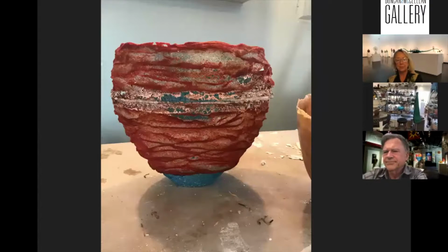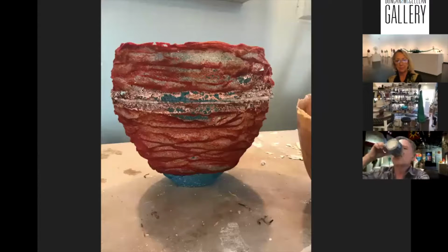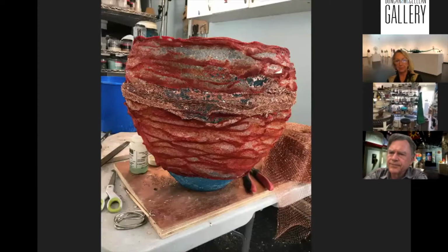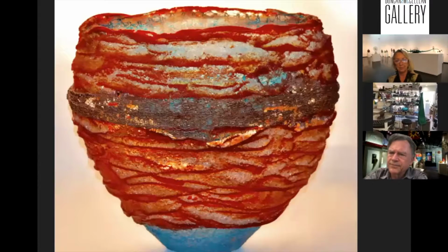Then I sit the two, one on top of the other, and I have to fit it. And after that, I'm going to solder those pieces together. I solder the two halves together, and then I'm soldering in copper mesh along the joint. Once that's done, it's going to go back in the plater and get plated with copper again to cover the joints, build up the copper, and make it strong. And that's the finished piece.